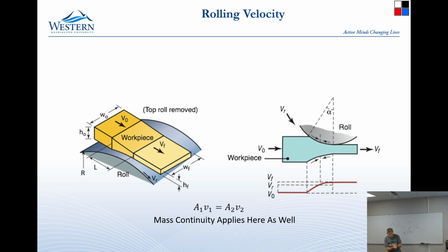So we have this foil, and because of friction, we're down here at 1.15 times sigma f. It turns out that as the material gets thinner, the roll that you have to use to roll it has to get smaller in diameter. And with foil, you are down in such a small range that the diameter of the roll has to be really small. So they can't actually make that small a roll and have it apply pressure. So what they do is they take two pieces of foil and they put them together. The other thing that they're doing here is that the roll is so small that it's hard to apply 1.15 times sigma f down on the piece of material.